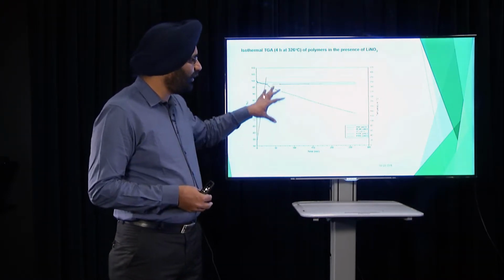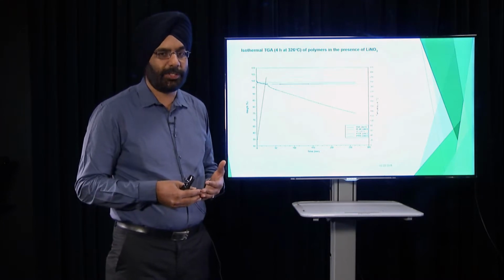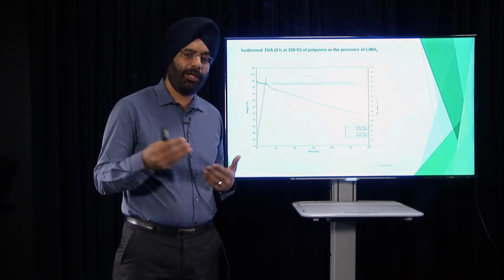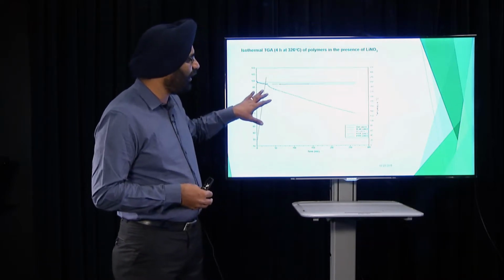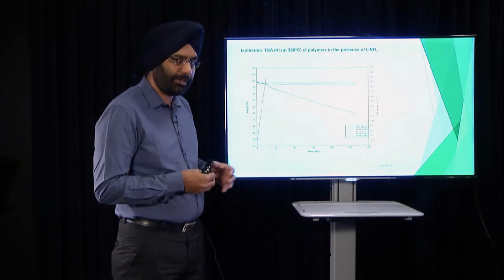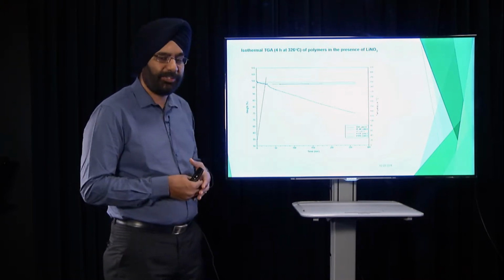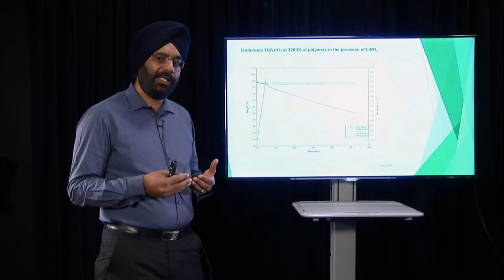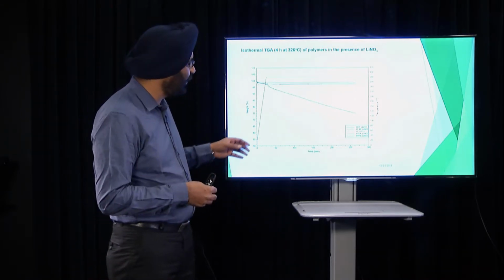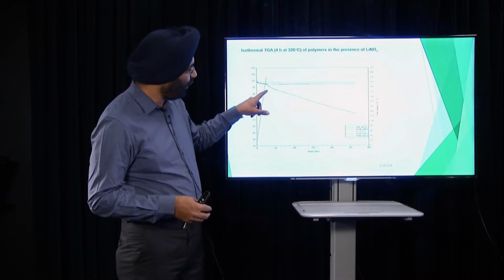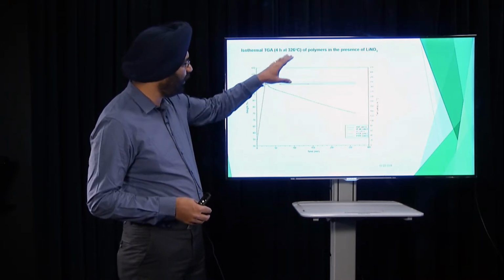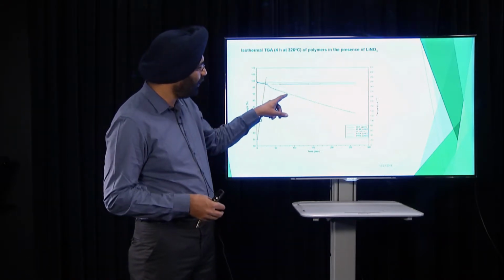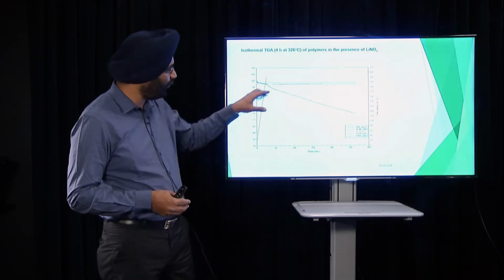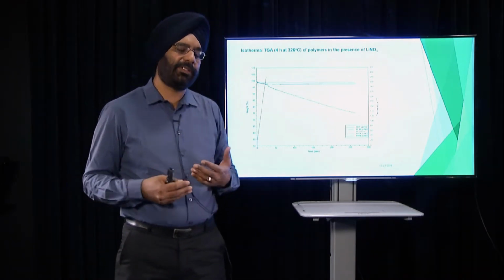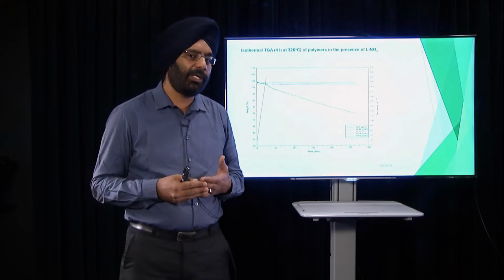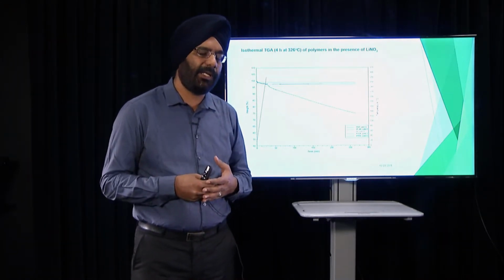We studied different materials in the presence of salt and kept them at a certain temperature for a very long period of time. Again, we wanted to see if there is any kind of decomposition, any kind of reaction between the encapsulating material and the phase change material. As you can see between these two lines, when we kept it at around 326 degrees C, two materials showed some weight loss. That clearly told us that there is some kind of reaction going on between the phase change material and the selected material.